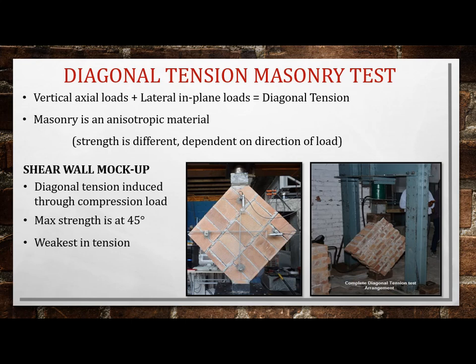So another test, this is a shear wall mock-up. Shear walls are induced with vertical axial loads and lateral in-plane loads, and they create diagonal tension. Masonry is an anisotropic material, meaning it behaves differently depending on the direction of the load. So this particular test, these are older tests. There's been empirical data. This is not a frequent test, but enough has been done that these types of laboratory tests over the last 30, 40 years make the design values in the manuals we use. This is a diagonal tension induced through a compression load, and it shows that the maximum strength of masonry is at 45 degrees. Masonry is weak in tension, strong in compression.